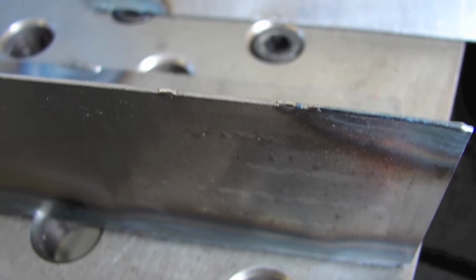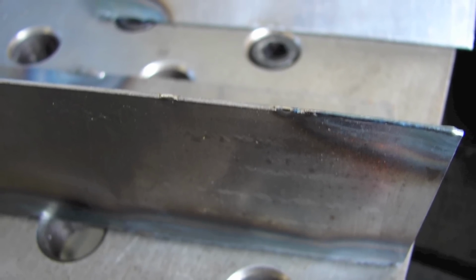All right, here's an outside corner joint on 18 gauge. That's roughly 48 thousandths, just regular old carbon steel. That's that fan on demand running in the background again. That booger's a little bit loud for my taste. All right, on an edge weld, the Miller has excellent low-end arc characteristics. I can run a bead on 48 thousandths steel. This is the bottom end. I had the panel amperage set on probably about 100, but still was able to control it.